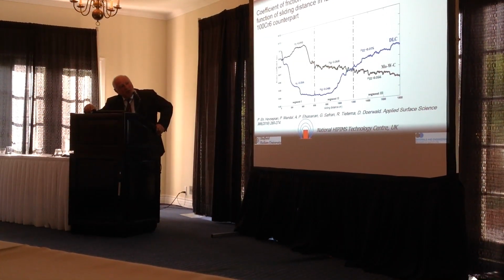The friction coefficient does reduce because you generate more and more of this lubricious phase with time.